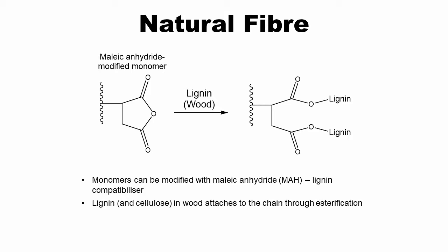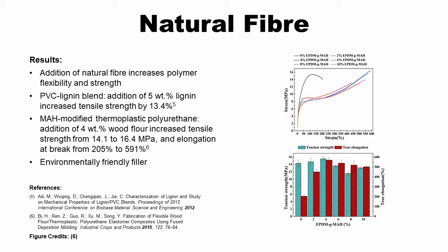This modifier has to be introduced before polymerization, and the subsequent esterification reaction produces a covalent attachment of wood to the polymer matrix. This enables interchain cross-linking via the wood particles. Blending natural fiber with various polymers has led to an improvement in the polymer structural properties. Adding 5 weight percent lignin to PVC increases tensile strength by 13.4%, and adding 4 weight percent wood flour to polyurethane both increases its tensile strength and nearly triples its elongation at break. All of these filler materials are abundant in nature, environmentally friendly, and safe for humans to use.